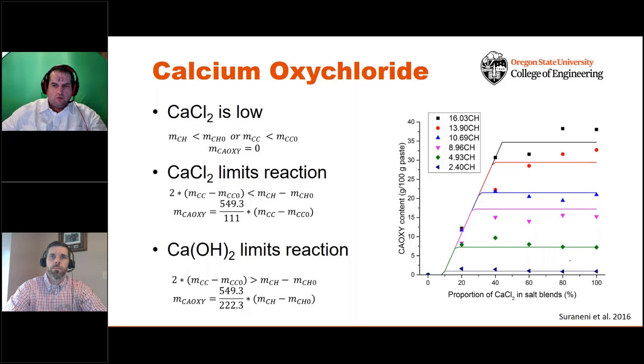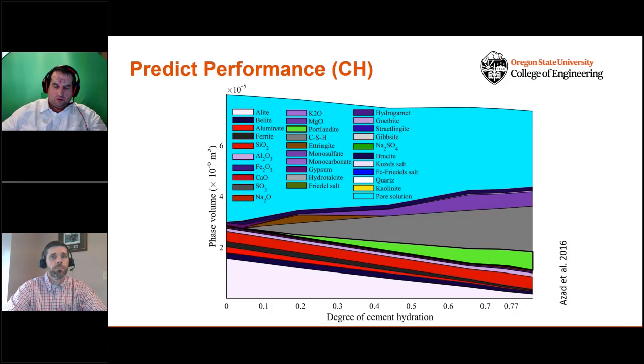Now, not surprisingly, what we would expect is different types of reactions occurring when we have a small amount of calcium chloride, a medium amount of calcium chloride, or a higher amount of calcium chloride in the system. What I've just shown here is that at low levels, we have very little reaction. We then have a transient phase until the chloride reacts with all the calcium hydroxide. And then we get to these high levels over here. Again, systems without fly ash have a very high amount of oxychloride. Systems with fly ash have a very low amount of oxychloride that's damaging the overall system.